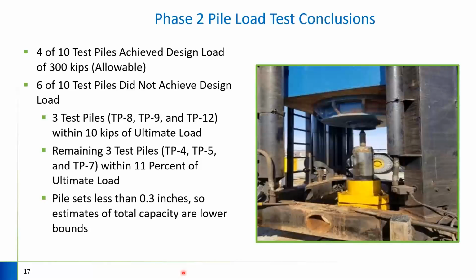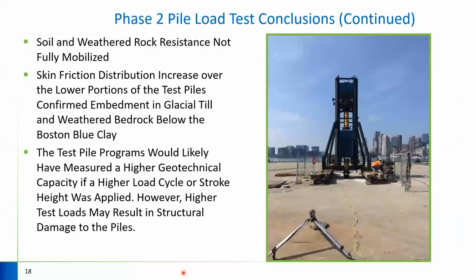And the main reason for this was because we had such high loads in phase 1 with the 24-inch drop height that we did not want to overstress these piles and lose any monetary contribution to the final structure that the owner would realize. So for the pile sets in general, these were less than the 0.3 inches as discussed. And so in our final report, we determined that these were lower bound estimates of total capacity and that we could get significantly higher loads.